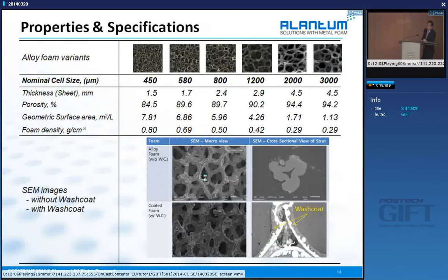These are the properties or specifications. I mentioned that it depends on the pore sizes of the polyurethane. So right now, our pore size ranges from 450 microns up to 3,000. So depending on the pore size, we are making the kind of thickness from 1.5 millimeters up to 4.5. But nowadays, we are also developing a much coarser form, like 5,000 microns pores. Then we have 10 millimeters.